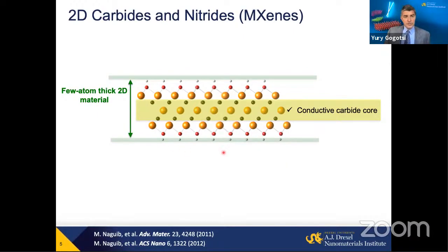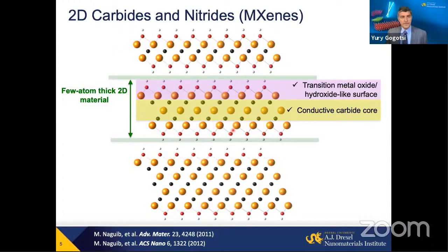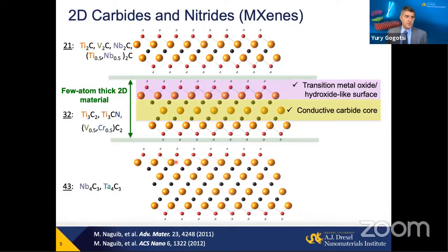Moreover, you can actually change the surface chemistry of this material, and you still can keep their conductivity. Unlike, say, graphene, when you transition to graphene oxide, described by Rick Kaner and others today, you basically kill the conductivity completely. Moreover, these transition metal oxide surfaces can also change the oxidation state of transition metal atoms. And you can basically use it for energy storage or other processes. And they come in a variety of flavors. So you can have materials with 2 layers of transition metal, 3, 4. We call them 2-1, 3-2, 4-3 structures. They can have a variety of elements on the M side. So M in MXene stands for transition metal, X for carbon or nitrogen, and we pronounce it MXenes for easy pronunciation, like a lady's name.